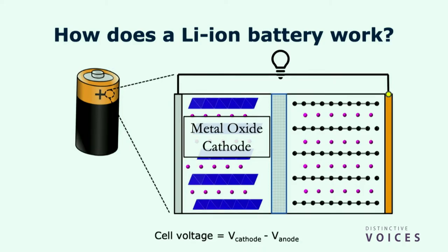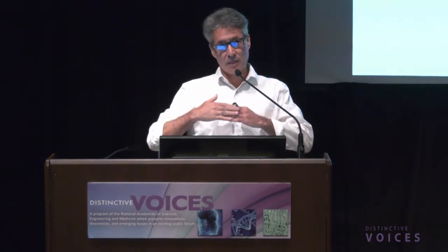And because it's a layered material, lithium ions can move relatively easily in that plane, sideways, basically in this orientation. On the anode side, there's basically just one anode that works quite well right now. That's the graphite anode. And for the same reason that when we write with a pencil, we exfoliate graphene layers as we drag our pencil tip across a piece of paper, that kind of bonding that allows that easy exfoliation of graphene also makes it easier for lithium ions to go in between the graphene layers in graphite.